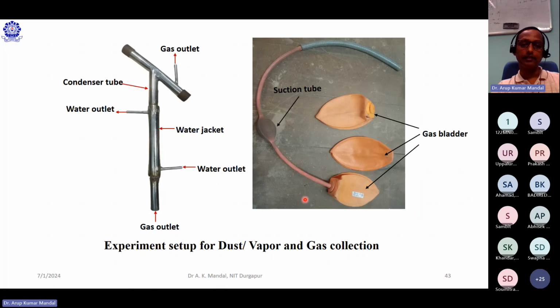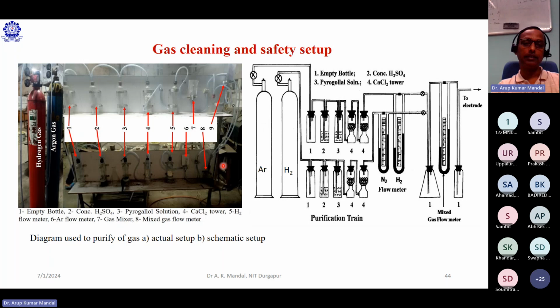So for gas collection, we used one water-cooled jacket where the gas is passed through this jacket, and when it turns, direction is changed, the solid particles settle down here. Okay, and from the gas outlet, we suck this gas from the bladder and send it for analysis. This is the gas cleaning setup, because hydrogen along with the argon is used, therefore some cleaning is required to avoid the explosion.